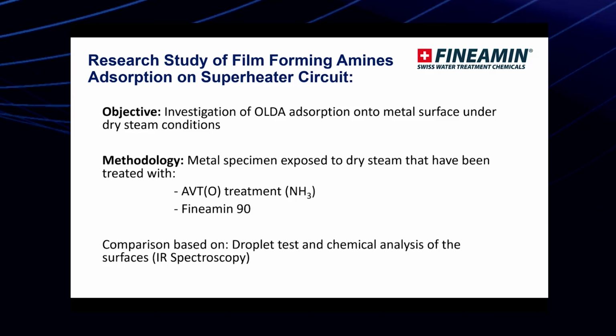So the methodology is we have metal specimens that will be exposed to dry steam that have been treated with either AVT-O, in this case AVT-O treatment of ammonia, or Fineamin 90. Then we will compare the results based on the droplet test, and we will do chemical analysis of the surfaces. We will try to do different analyses, but eventually I will end up with the IR spectroscopy based on the results from Japan.